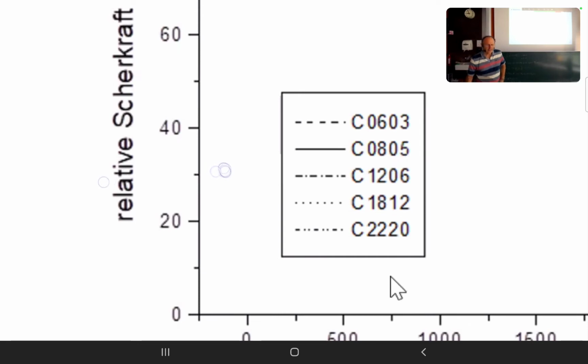So here, that's different sizes of the capacitor. 0603 at that time was a relatively small capacitor. In the meantime, the smallest capacitors we have as a discrete device are roughly a factor 10 smaller. But on the other hand, we also know bigger devices have bigger problems. So it was not necessary to look at the smallest ones. And then we can see how the initial strength is reduced over number of cycles. And in the worst case, maybe it goes down to 60% of the initial strength we have in that attachment.